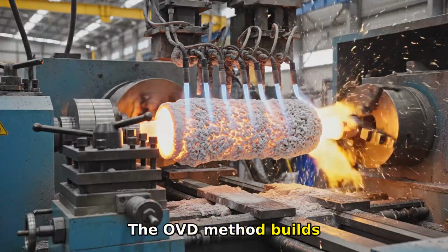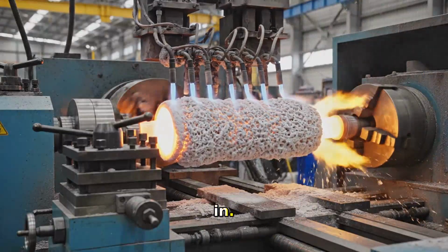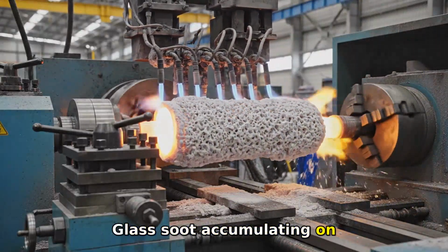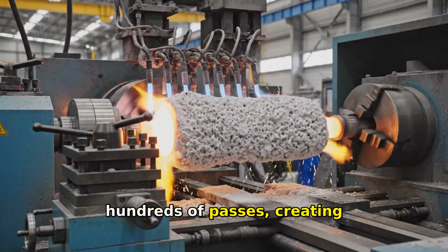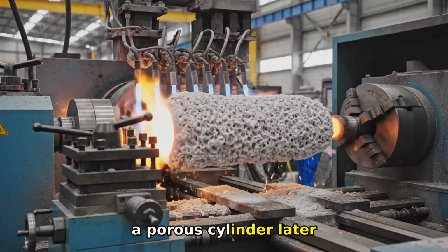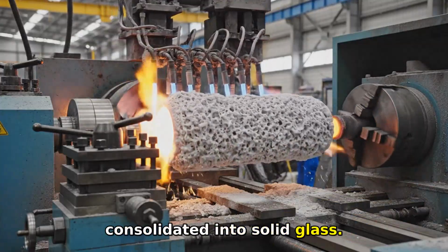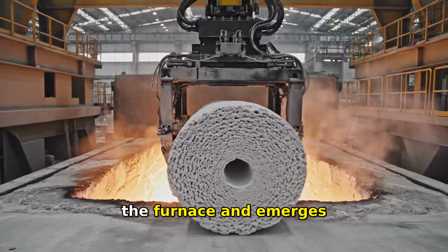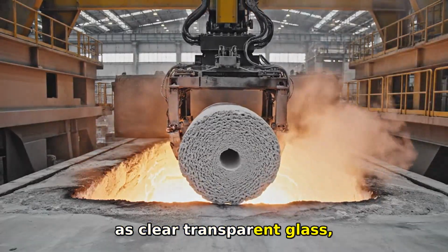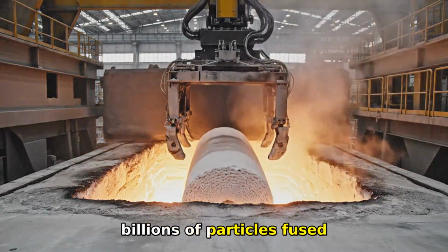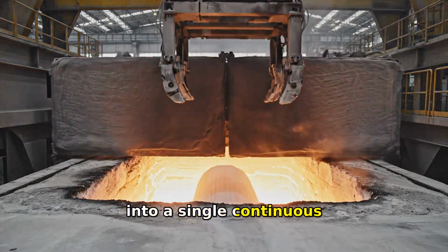The OVD method builds preforms from the outside in. Glass soot accumulating on a rotating mandrel in hundreds of passes, creating a porous cylinder later consolidated into solid glass. White opaque soot enters the furnace and emerges as clear transparent glass. Billions of particles fused into a single continuous solid.